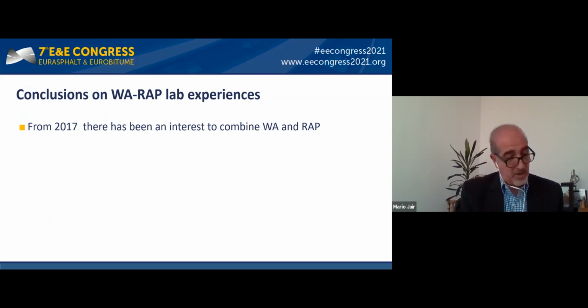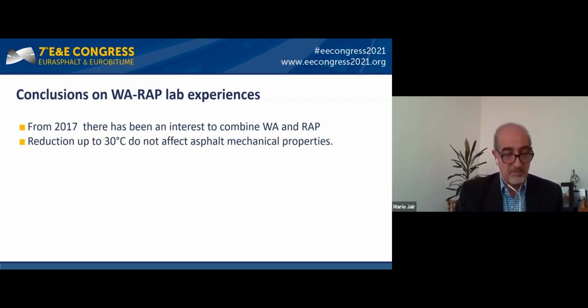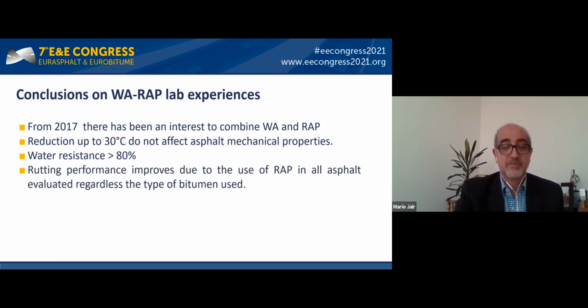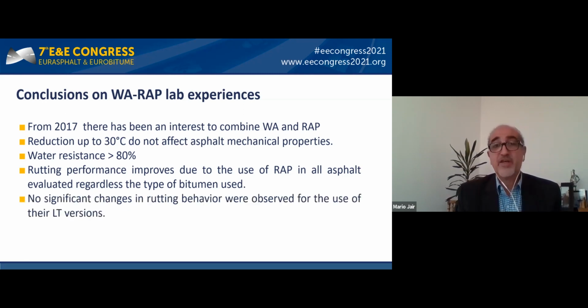The findings of the development of warm RAP options evaluated in lab are as follows. We could see that reduction up to 30 Celsius doesn't affect asphalt mechanical properties. Regarding water sensitivity performance, the retained resistance was always greater than 80%. In terms of the rutting performance, in all cases it improved due to the use of RAP in all asphalts evaluated, regardless of the type of bitumen used. No significant change in rutting behavior was observed for the use of low temperature binders.